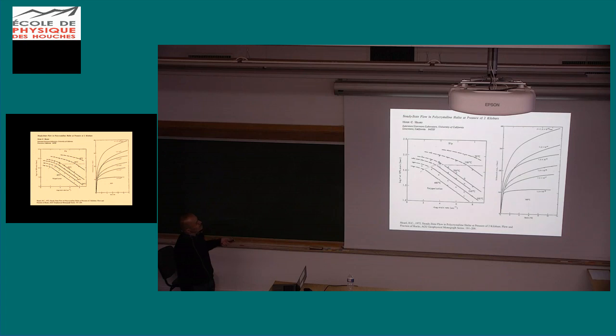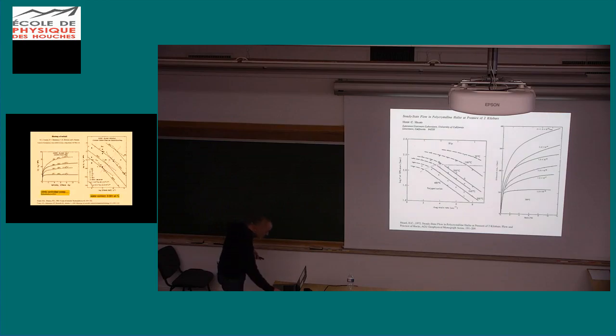And what he has produced is a lot of stress-strain curves at 2 kilobar pressure, so there was a lot of confining pressure on the salt, and he has seen that there is a kind of power law relationship at a lower strain rate between differential stress and the strain rate.